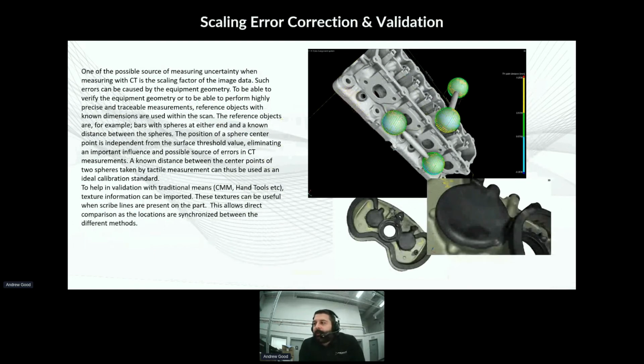Now, the big thing is there's always, yeah, that's great, there's a measurement. How do you prove it? The beautiful thing with CT is because it's all digital, you can provide traceable proof by using what's called IQIs, or you can use reference objects. In this particular case, we're using ball bar spheres, because a sphere's center is independent from the surface threshold value, which is very important because that removes any possible sources of error in the imaging chain. So a known distance between the center points of two spheres can be measured, adjusted, and also verified using traditional means.